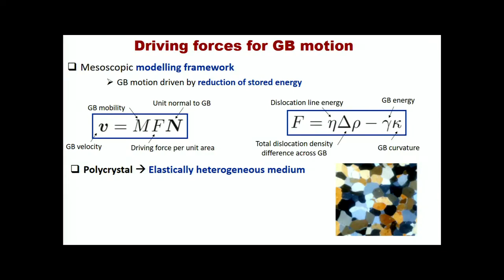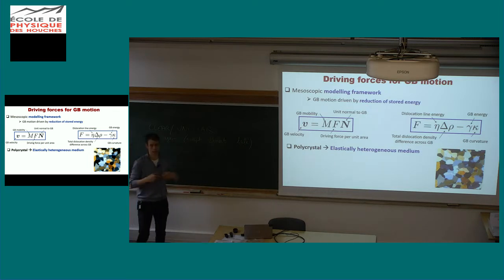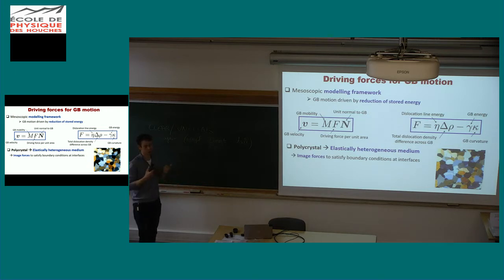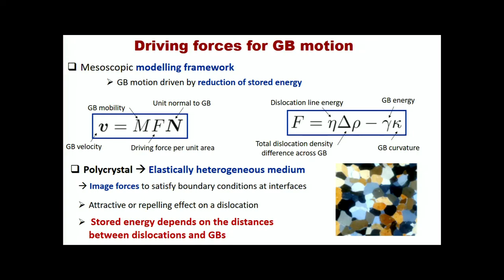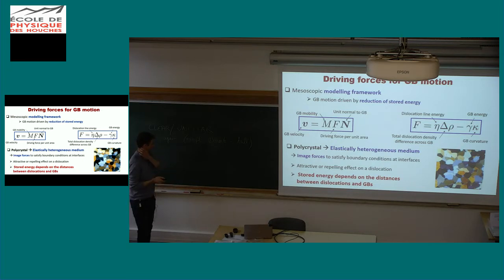Generally the stored energy term is computed as the dislocation line energy times the difference of dislocation density between both grains. If you look at a polycrystal and consider anisotropic elasticity, you have different elastic moduli inside each grain due to their different orientation. Because grain boundaries are a perfect interface, you have to satisfy continuity of displacement and traction vector, so you have image forces to satisfy these boundary conditions. This means, if you consider a dislocation in an anisotropic medium and add an interface, you will have additional force which can have attractive or repulsive effect. More importantly, the stored energy — which is the elastic energy due to a dislocation — depends on the distance between dislocations and grain boundary. This is the main subject of this presentation.